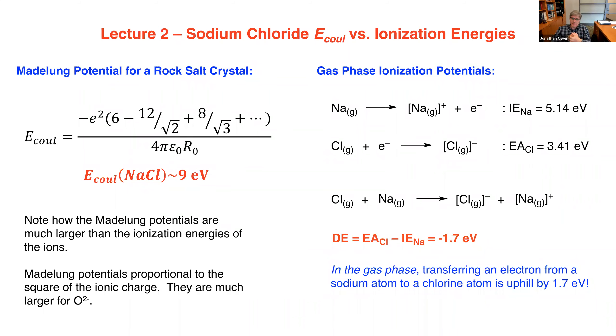So sodium chloride is very, very stable — and where does that come from? It's mostly about the Madelung potential. It's uphill to transfer an electron from sodium to chloride, but when you take those ions and form a rock salt crystal, you get about 9 electron volts of energy released. This is what it would be without polarization — just a Coulomb energy calculation. In reality, the atoms polarize within the crystal, which reduces that energy slightly. There's also some covalent bonding and orbital overlap in sodium chloride that leads to bandwidth development.